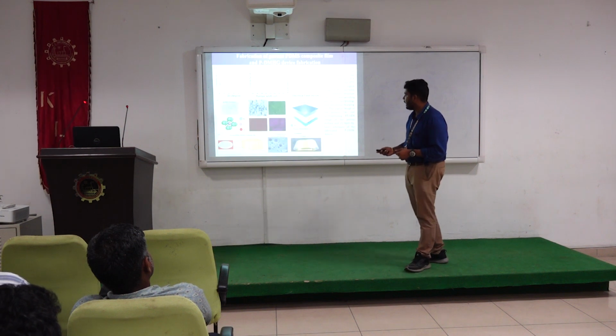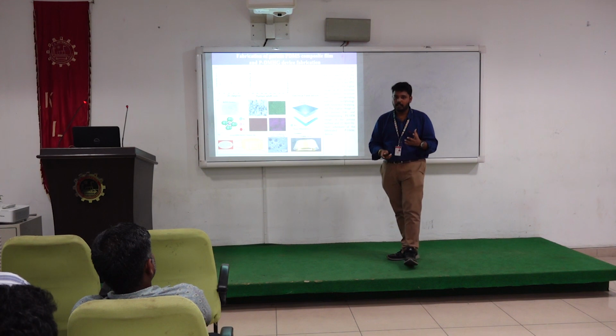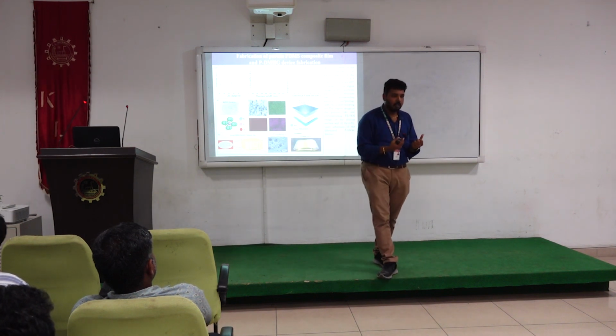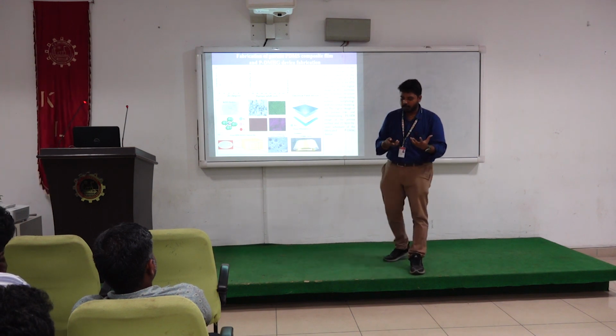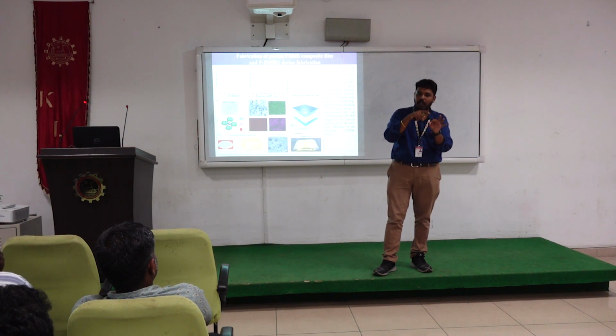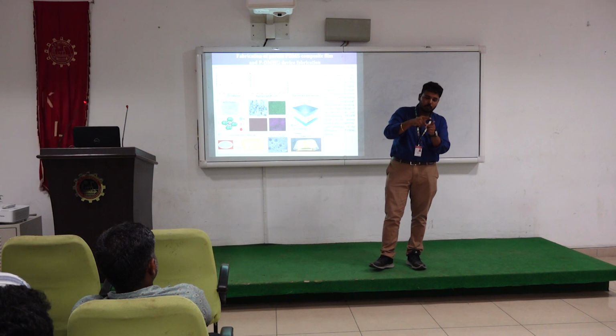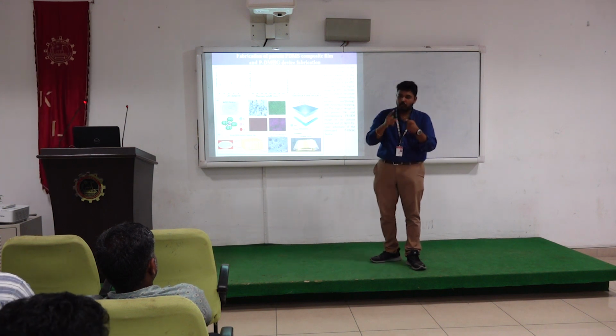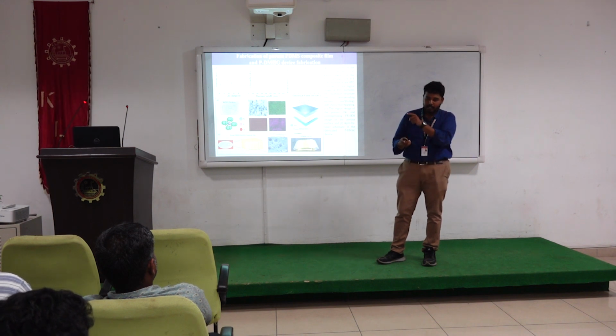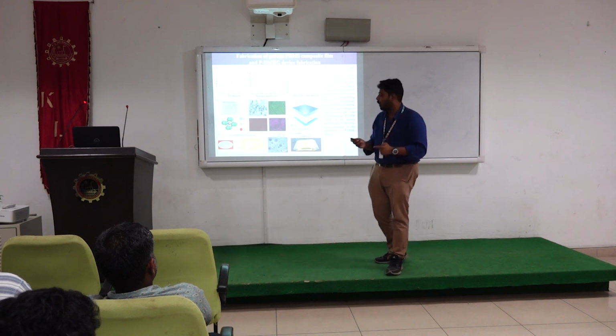So the next one is again we go for one impact sensor. Here we have used barium titanate. The barium titanate I made like a porous composite film. So I created pores on the composite film. Why I go for this approach is the pores can trap charges. Because when I apply pressure, these pores also go for contact and separation, where some of the charges can be trapped and the trapped charges will eventually be released, so there is a chance to increase its output.